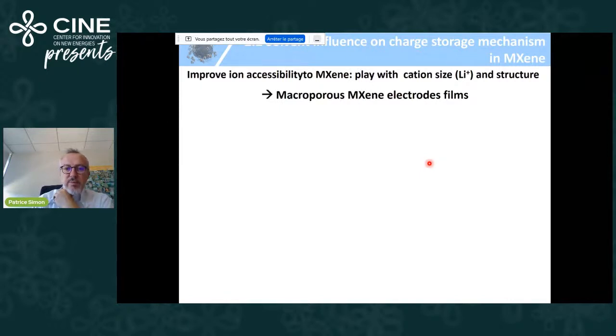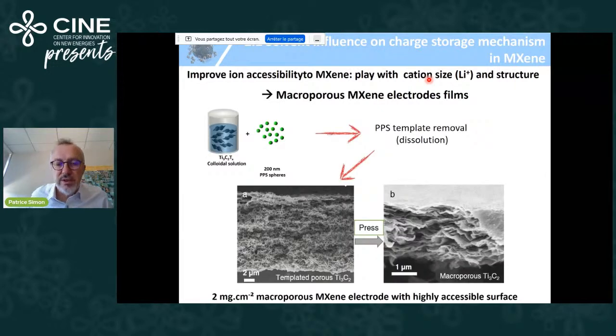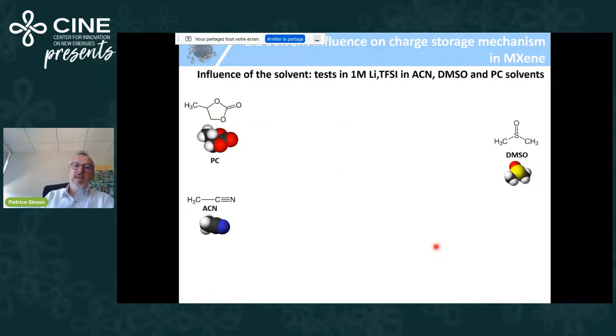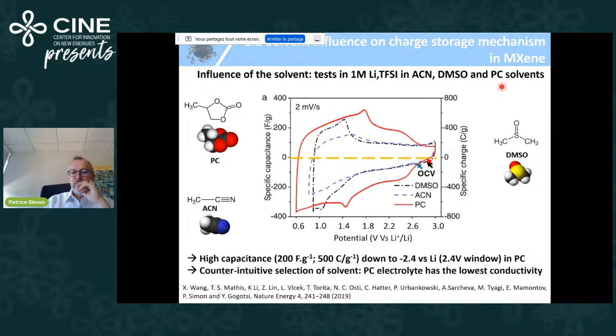So the first thing is that we prepared macroporous MXene electrodes because we wanted to play with lithium intercalation from non-aqueous electrolyte. Obviously, these are bigger ions and a more viscous electrolyte, so we want to prepare macroporous MXene electrodes. We did it in a very simple way. You mix polystyrene spheres together with Ti3C2, and you make a filtration. You see you have your electrode, and then you dissolve the polystyrene spheres in acetone, and you have these big pores. You press a little bit, and you end up with your macroporous Ti3C2 electrode. And then we use a salt, lithium TFSI, and we used three different solvents: acetonitrile, DMSO, and PC. And these are the results we obtained.